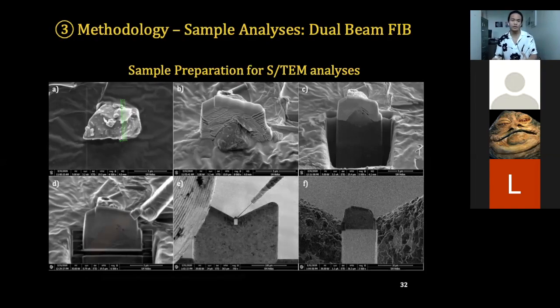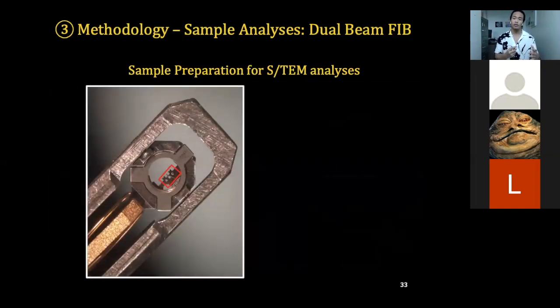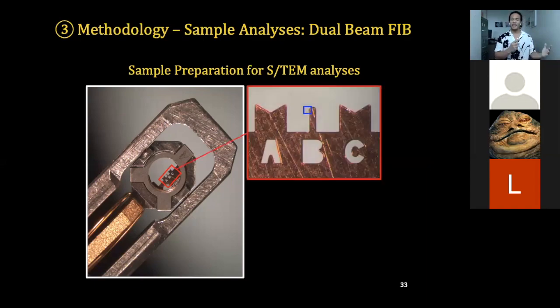This sample then goes in a double tilt holder, which will go to the next instrument. Again, I'll explain that later. In the middle of that double tilt holder is where the copper grid will go, where our sample is. The red box is an example of a copper grid. It's not the grid that we use, but this is just an example photo of the holder with the grid inside. A zoomed in image of that grid shows the letters A, B, C, which is useful for navigation because the sample is so small. So it allows you to find your sample quicker.